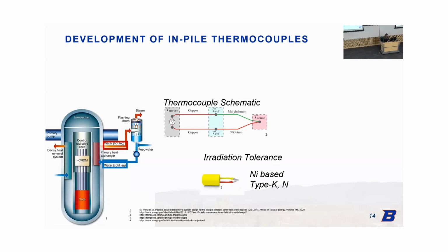One, when we think about irradiation-resistant thermocouples, like type K and N, which are nickel-based, when they're exposed to temperatures in excess of 1260 degrees Celsius, they start to decalibrate rapidly, largely because of chemical instability within their thermal elements, meaning that during accident scenarios, these thermocouples do not provide a reliable temperature measurement for the reactor technicians.